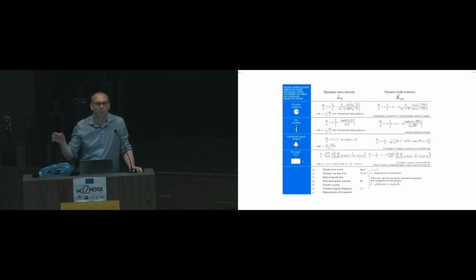I will just assume that the bulk modulus is equal to gamma P0 over phi, or something like that. And Zwikker and Kosten said, okay, we will take into account the thermal effect. So in air, we need to take into account the thermal effect and the viscous effect. In water, sometimes you can get rid of the thermal effect because it is so small compared to the viscous one that you can just forget about it.